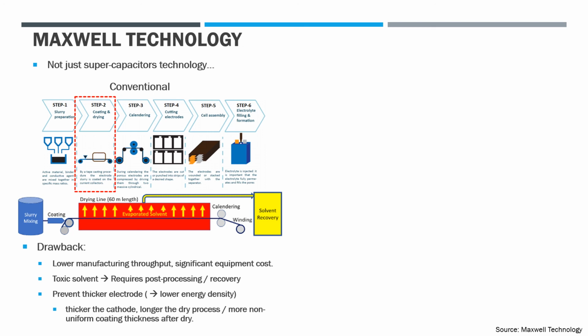The drawback of such a conventional approach is that because the dry line takes such a long time, it's lowering the manufacturing throughput, and also it takes significant equipment costs. And also because the solvent itself is toxic, it requires post-processing and recovery, which is also expensive. And the process itself prevents the electrode from becoming thicker, which essentially makes the energy density lower. This is because if you make the coating thicker, then it requires a longer time to dry. And also, when you have a thicker coating and then dry, the film itself would become more non-uniform, which is not ideal.